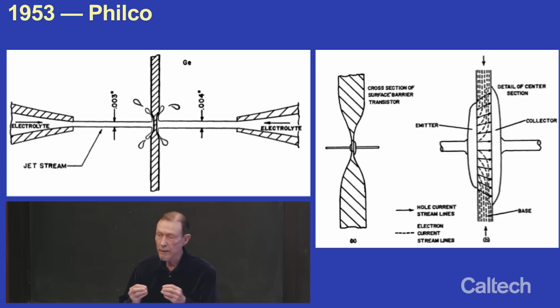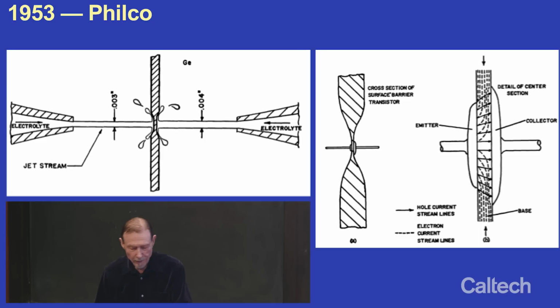And well, how do you know when to stop? Well, it turned out that germanium absorbs infrared light, and of course the amount you absorb goes exponentially with the thickness. So you shined light, this made a little light pipe, this electrolyte. You shined infrared light down one and looked at how much came out on the other side. It was very easy then to know when you get this much light, you reverse the polarity and you deposit the indium. And then they had this factory running.